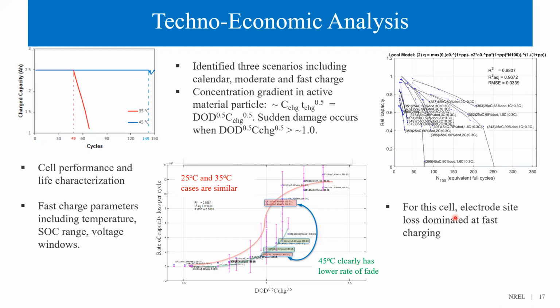To compare long-term battery use strategies, battery lifetime analysis is crucial. This was achieved with NREL's lifetime model. This model is a predictive model extending expensive lab battery aging datasets to real-world scenarios. The model's trial functions are statistically regressed to lithium life data sets where cells are aged under various conditions.